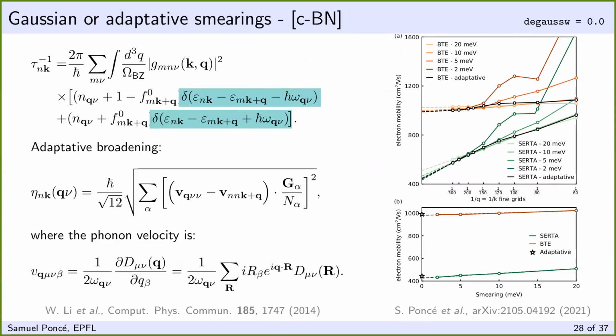Oh, hi. Hello. Yeah, I was wondering if you have tested the behavior of the polar optical scattering limited mobility with respect to screening, screening that is dependent on doping and carrier concentrations. Yeah, so in a way, the polar optical is included because we include all modes. So it's not something we have to add per se. In this case, I haven't studied it, so all the doping is always in the regime of this intrinsic doping where the mobility does not change as a function of doping because we are in this low carrier concentration limit. And basically the Fermi level will always be in the conduction band.